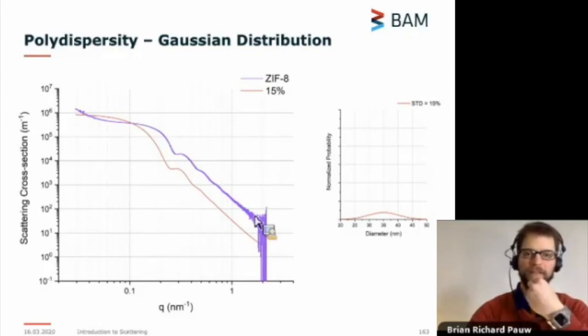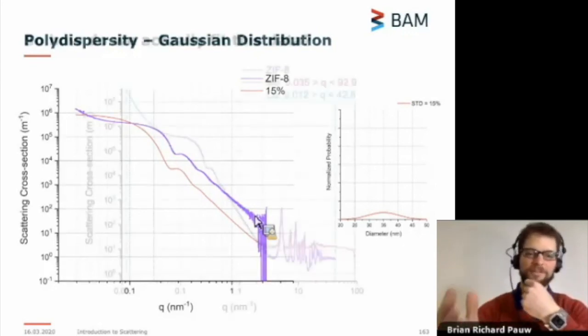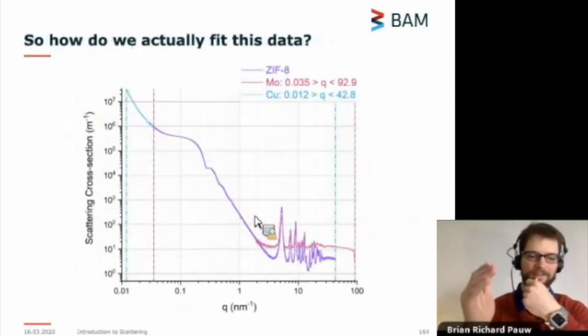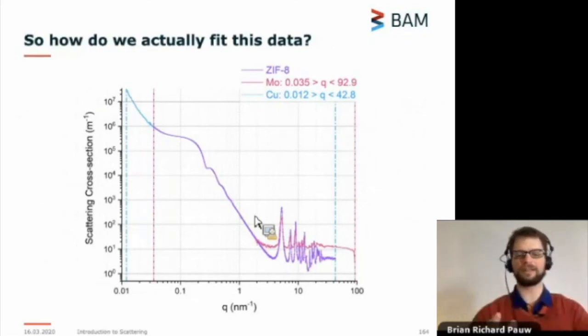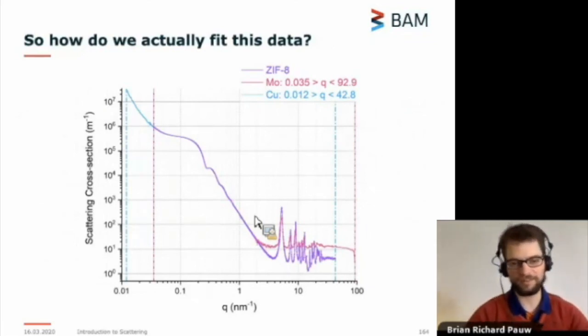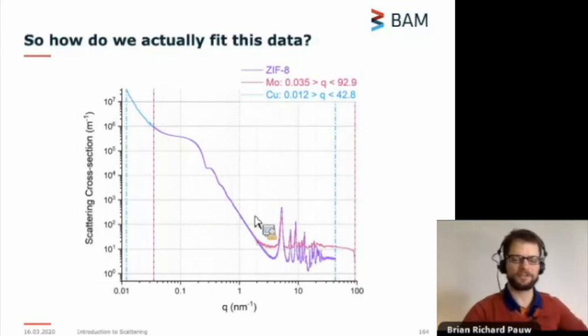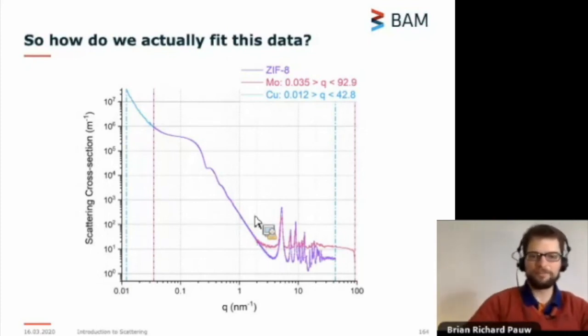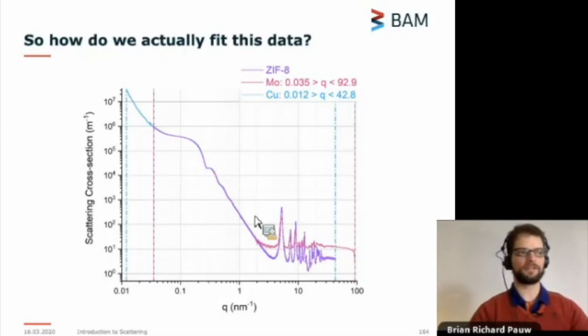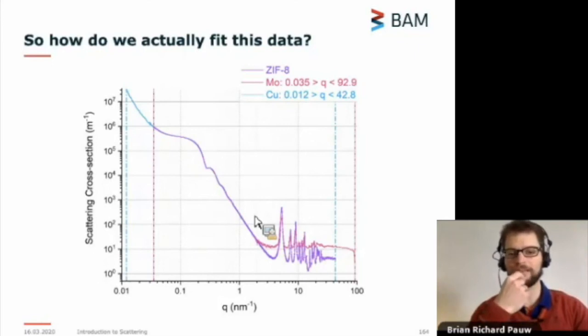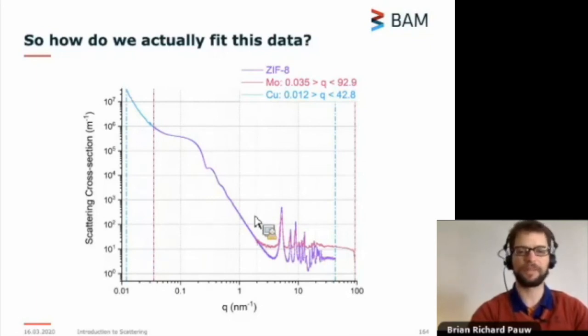So how do we actually fit this data? Well, I can't complete this story because to analyze a scattering pattern like this, it would take several weeks, if not months. It turns out these ZIF particles are not quite spheres, so you can't describe them with spheres. They're sort of more like dodecahedrons. And therefore you need much more advanced models to actually describe this. But in principle, it's possible. All right.